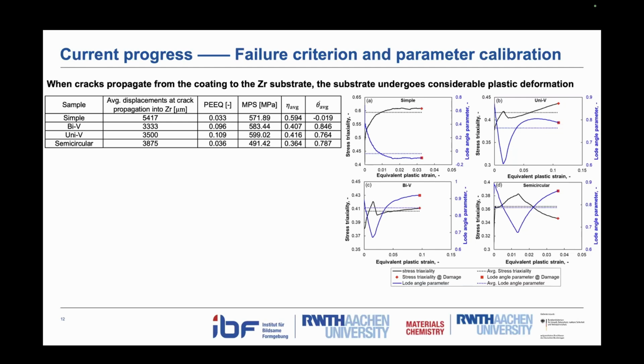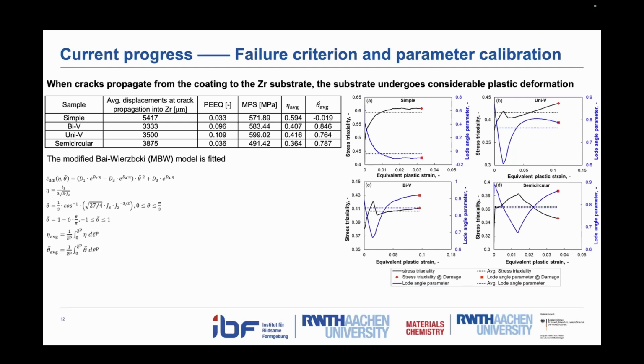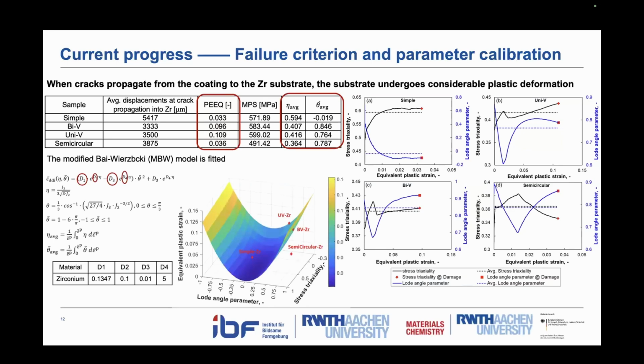And for this characterization, we have chosen the modified Bai-Wierzbicki model. So in this model, when the critical equivalent plastic strain is reached, the sample is damaged. And there are 4 parameters that we need to calibrate. So we calibrate these 4 parameters based on the equivalent plastic strain, stress triaxiality, and Lode angle parameter that we collected from the first round of numerical simulation. And we used MATLAB to help us with the calibration. And at the left corner, that is the calibrated data.